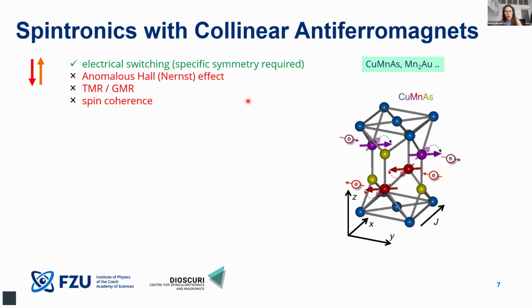However, in the collinear systems, there exists a class of materials which have locally broken inversion symmetry, such as, for example, copper-manganese arsenide or Mn2Au. And in these materials, a lot of fascinating things were demonstrated. Probably the most important one is that these materials, because of this staggered effective magnetic field, can be electrically switched. The magnetic order vector, the Néel vector, can be switched by electric pulses.